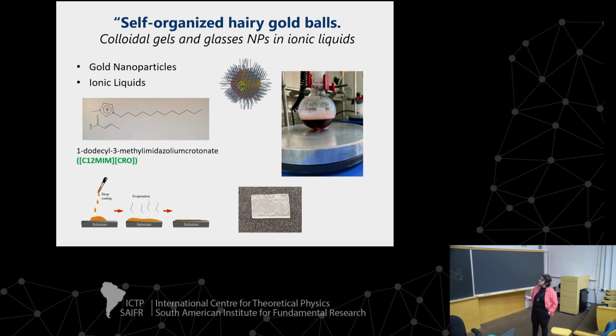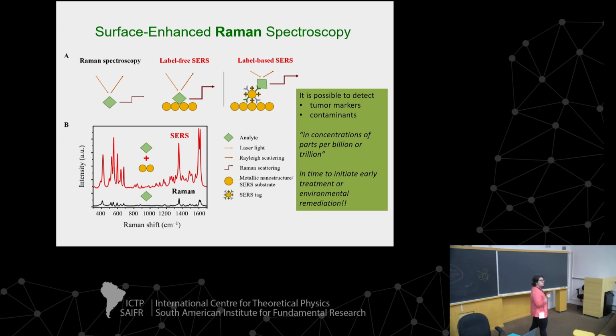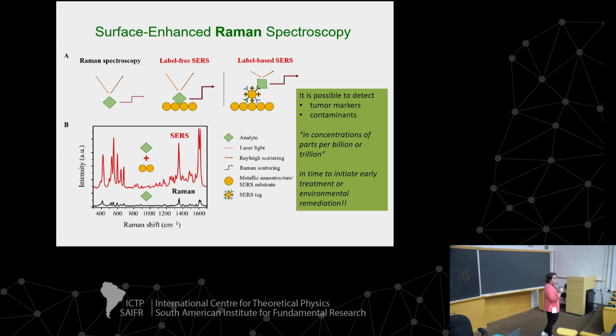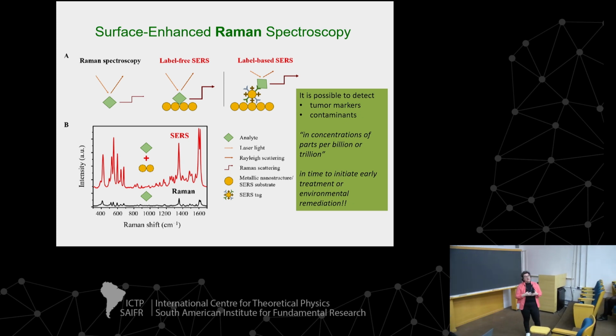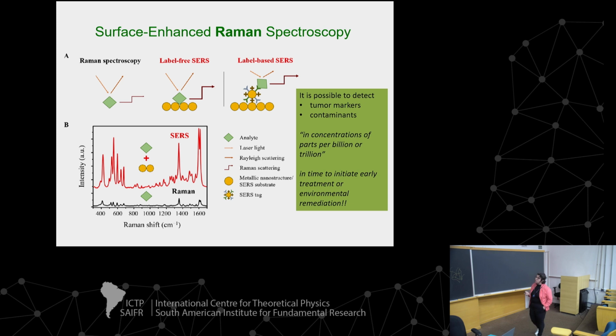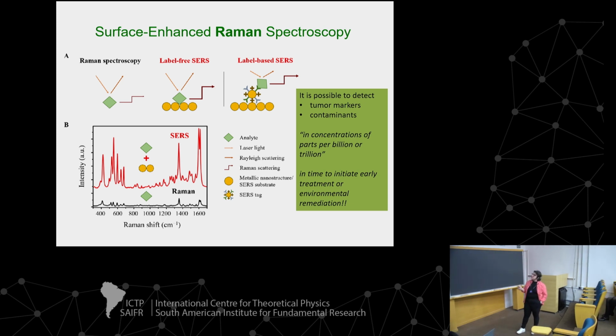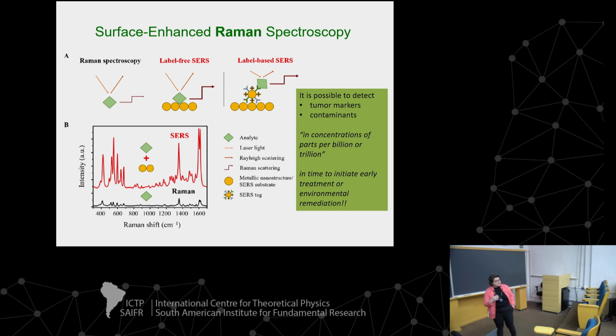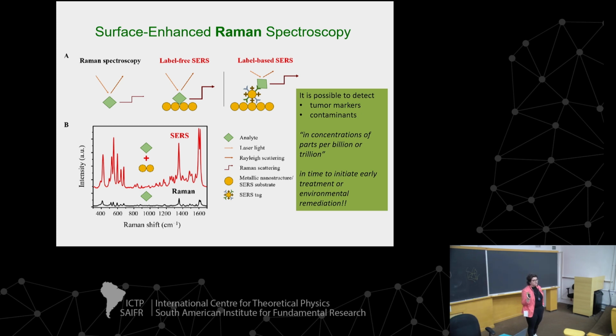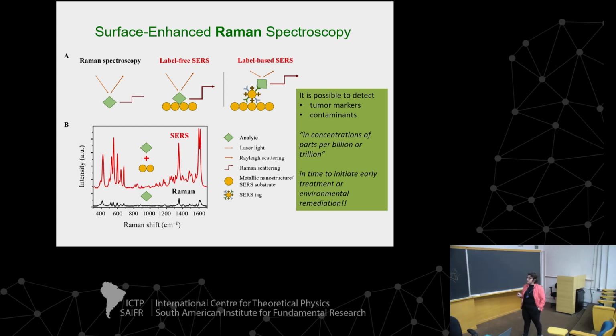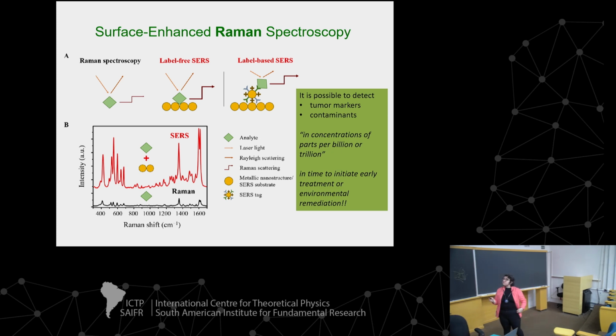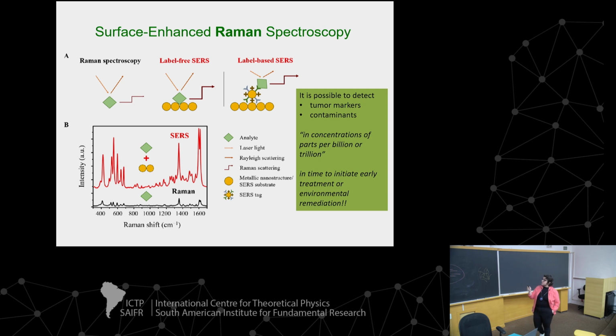And we use this to form films. We drop cast to form different kinds of films. Our main goal is to use these films as a sensor for low concentrations of contaminants and some tumor markers, with the goal of detecting concentrations in parts per trillion in time to initiate early treatment for cancer or environmental remediation before the concentration of the contaminant becomes a risk. We use Raman enhancement, a technique that uses the surface plasmon of the gold to increase the signals and detect concentrations in parts per trillion of the molecules.